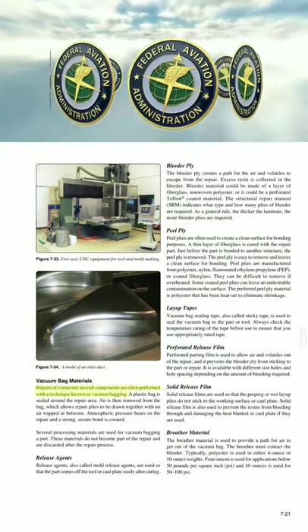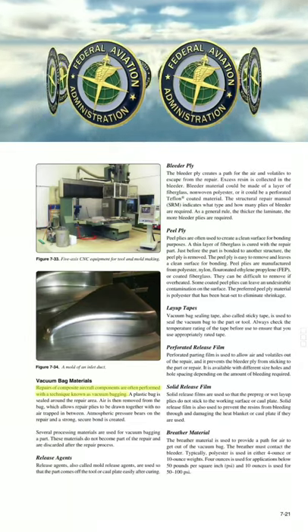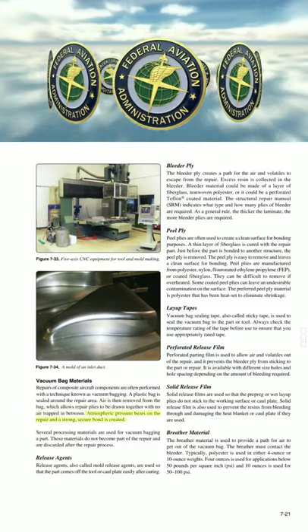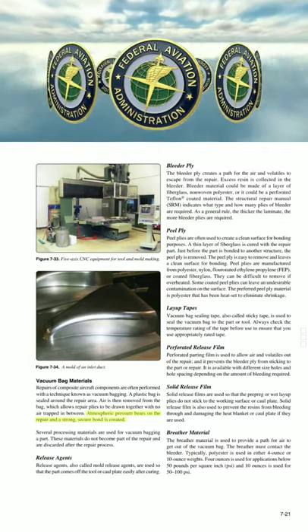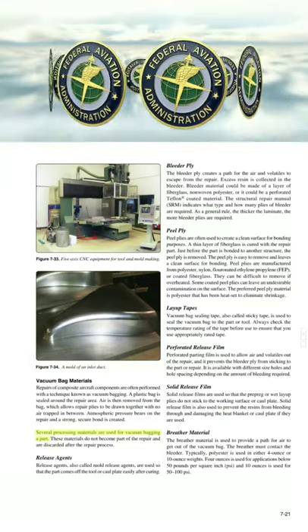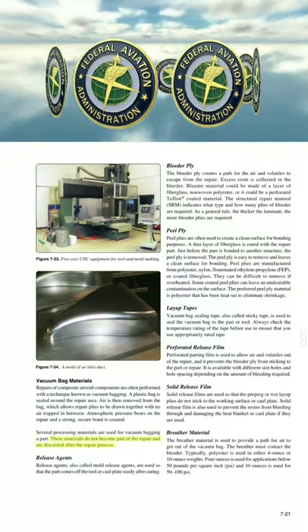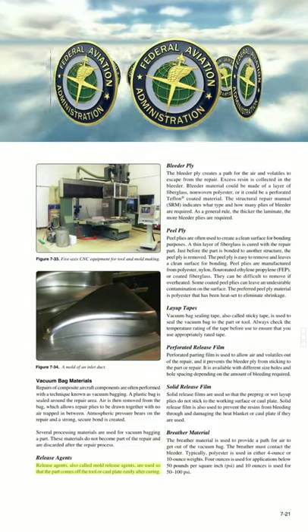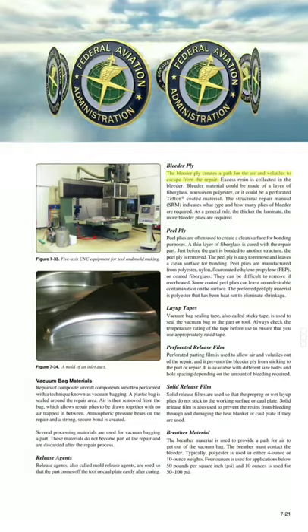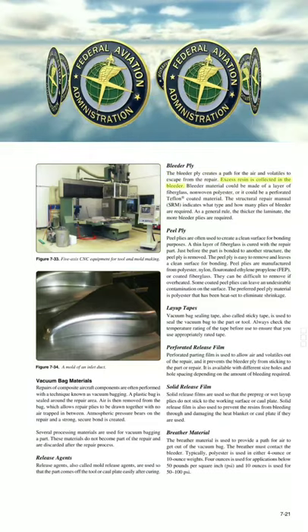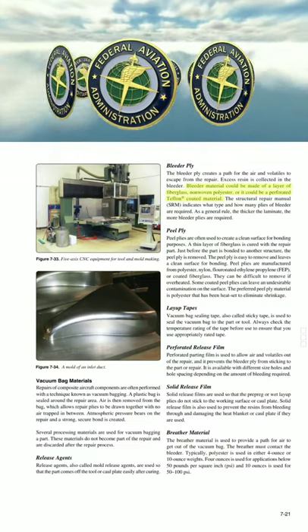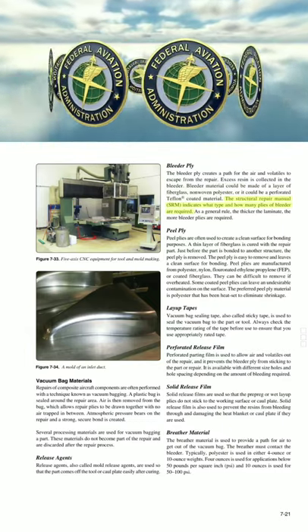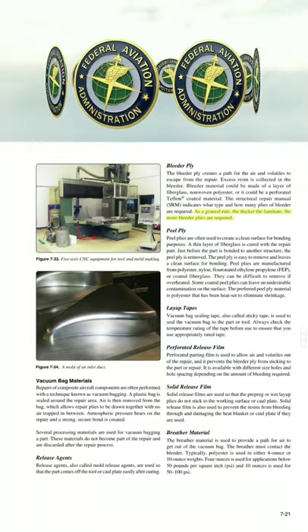Vacuum bag materials. Repairs of composite aircraft components are often performed with vacuum bagging. A plastic bag is sealed around the repair area; air is then removed, allowing repair plies to be drawn together with no trapped air. Atmospheric pressure bears on the repair, creating a strong bond. Release agents are used so that the part comes off the tool or caul plate easily after curing. Bleeder ply creates a path for air and volatiles to escape from the repair and collects excess resin. Bleeder material may be a layer of fiberglass, non-woven polyester, or perforated Teflon-coated material. The structural repair manual (SRM) indicates what type and how many plies of bleeder are required.